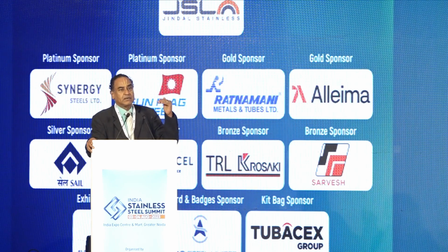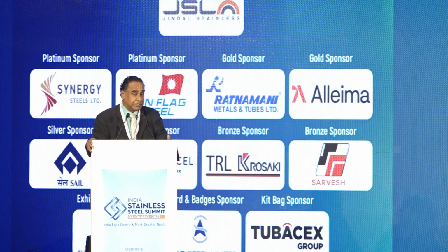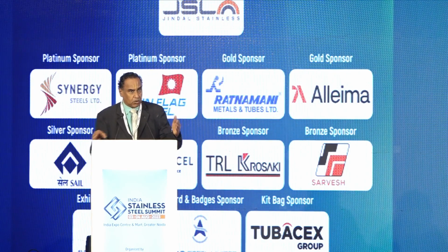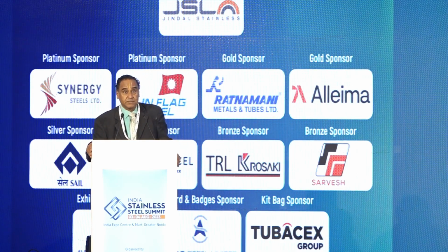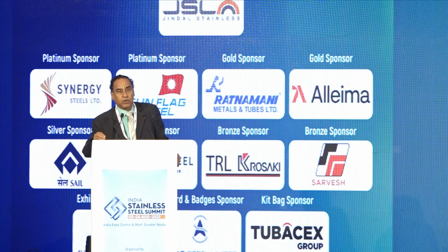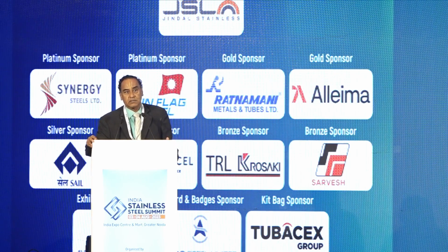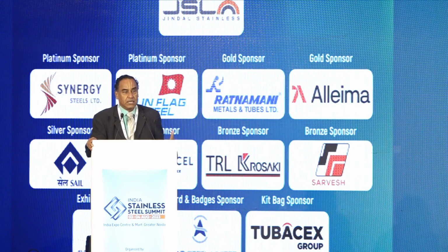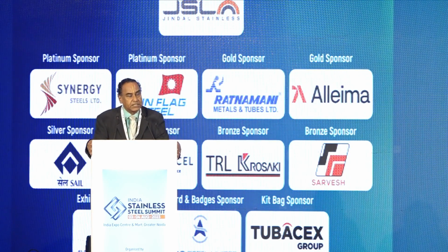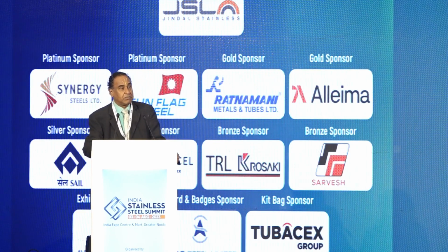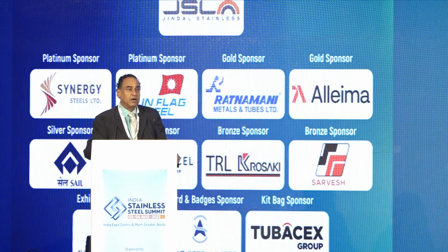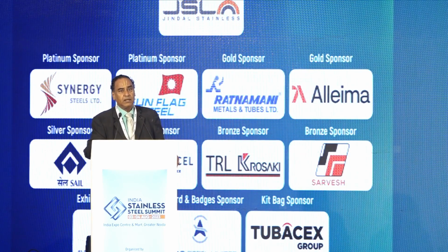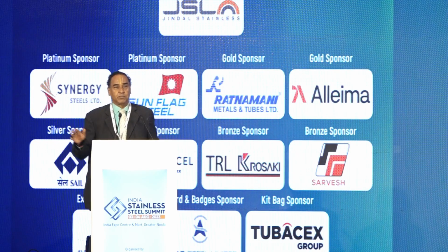In general, where the pitting tendency is high, for example in a chloride environment where the chemicals contain chlorides, the temperature is increasing and moisture is also present, then pitting resistance has to be imparted. Ferritic stainless steel has very good pitting resistance, from let's say 12 chrome, 13 chrome, 17 chrome, to 22 chrome. These are stainless steels in which the ferrite phase is stable at all temperatures, and they can be used up to a temperature of 400 or 380 degrees centigrade, subject to the earlier conditions that the corrosion rates are within limits at those process conditions, and the corrosion products are tolerated by the final product.